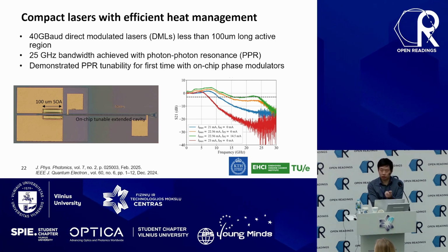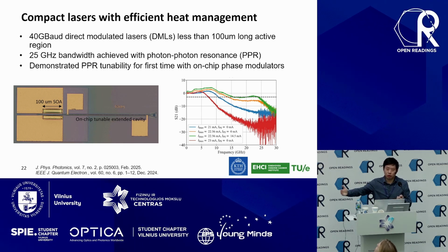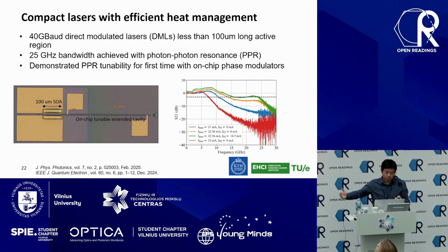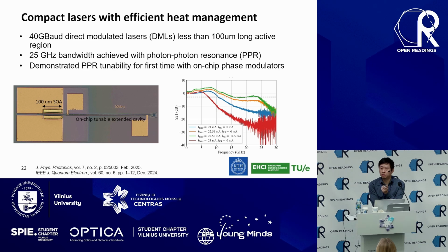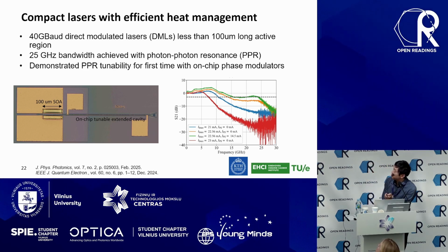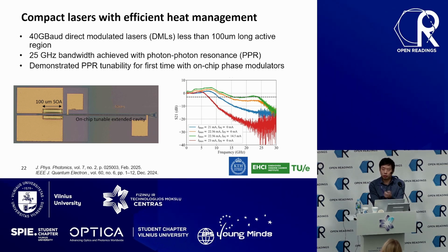And we can obtain this second resonance peak just by simply fine-tuning the extended cavity with this on-chip phase shifter. It's all about the phase matching between the two cavities. And when you have the right phase matching, you have the second resonant peak rising up, and you can extend your laser modulation by, in this case, almost 5 times, right? So we demonstrated 25 gigahertz bandwidth laser modulation, which can support 40 gigabaud data transmission.